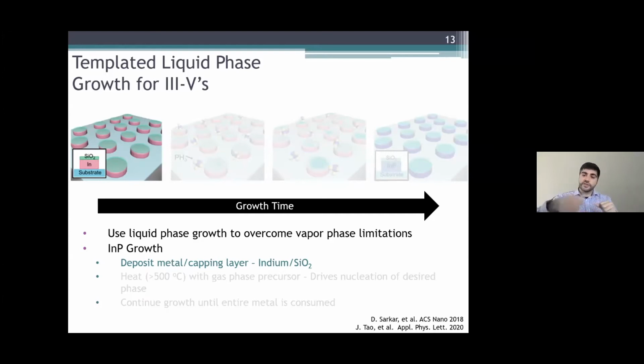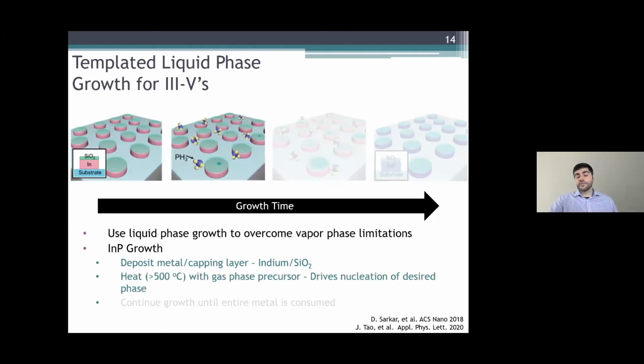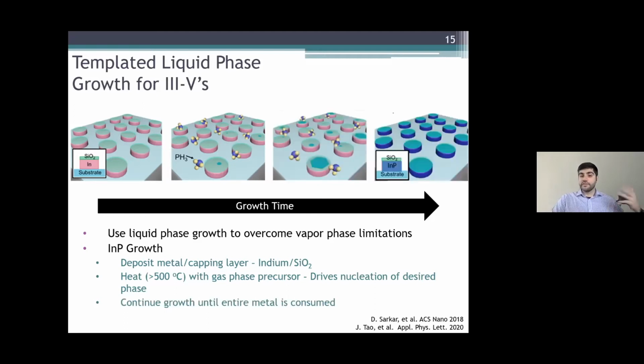Then we start introducing phosphorus to it, so we're going to indium phosphide. Just like when you add salt to water, you eventually supersaturate the water, and salt crystals precipitate out. Here, we supersaturate the liquid indium, and indium phosphide precipitates out. And you keep growing, and it consumes the template, and you're left with a single crystalline domain in your original template area.